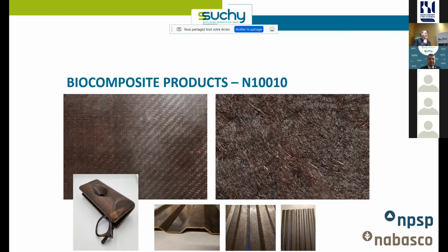The latest material we work with goes to 100% biocomposite material, where we work with a furan resin with, for instance, hemp or flax in non-woven and woven form. And here we start to set up the pre-preg production lines and also the product development, so which products to make from these materials. Especially the processing of these materials, we gained the knowledge to do that from the SUCHY project, for instance.